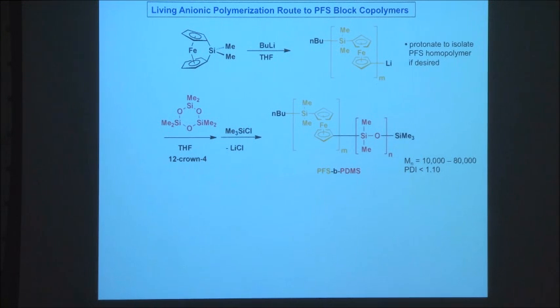And this can be achieved by a number of methods, but the method I'm going to describe is living anionic polymerization. So you treat this monomer with butyl lithium. It will ring open: the butyl group will attack silicon, butyl minus attacks silicon, you open this bond, and you generate polymer chains which have a lithiated chain end, and the butyl is at the other end of the chain. And this is a living polymerization because these polymer chains are stable in solution.